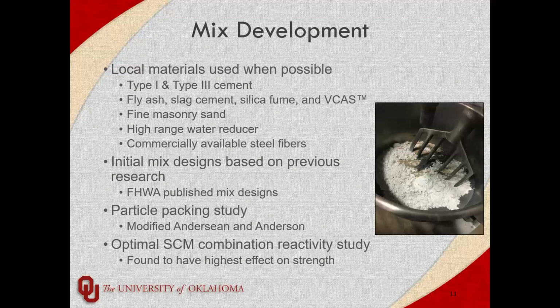So when we went through that, a lot of the published research at the time showed that the particle packing was very important, arguably the most important thing with UHPC outside of the water cement ratio to give it the strength and durability that it has. But one thing we found was that our particle packing study didn't actually increase the strength much above some of our other studies that we did, just changing the cement types and things like that. So it didn't seem to have as much of an effect.